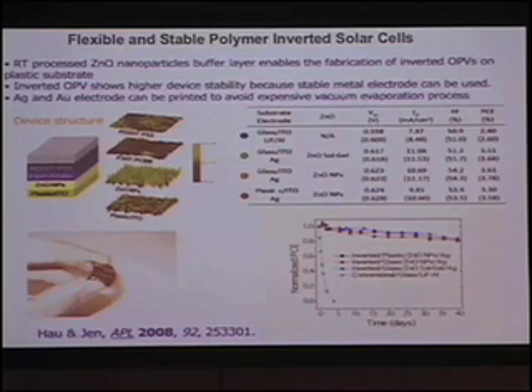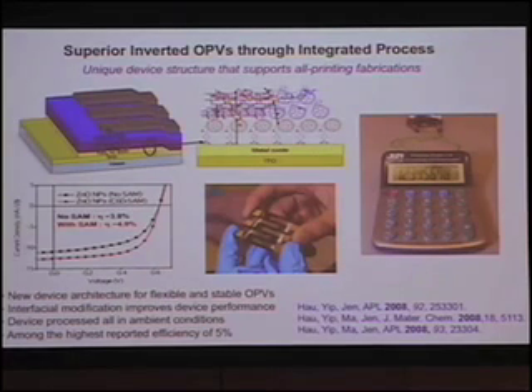But one of the very surprising results we discovered from this: when you make this device based on the polymer substrate without any encapsulation, and if I make this device with a conventional device structure, in 4 days exposed to the outside environment, this device would completely die. However, if you have this device utilizing the inverted polymer structure, even after 40 days you still have more than about 85% of your device performance remaining. So by changing the sequence of your device configuration, you can greatly improve your device performance and also the stability of the device.